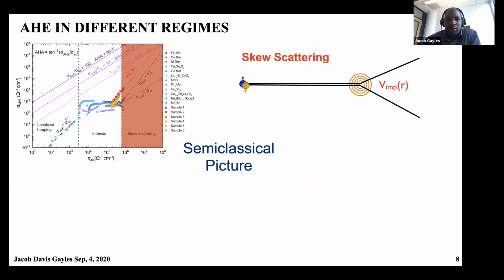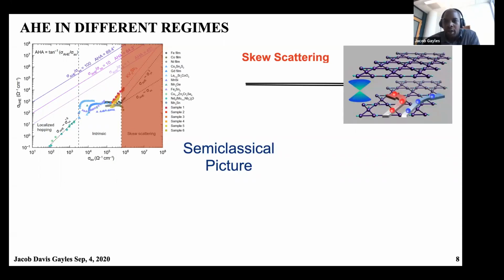Skew scattering is a picture of diffuse scattering that looks just like Mott scattering, where the spin of the electron is deflected by an impurity, and this impurity has a magnetic potential, so it deflects electrons with different spins in different directions. And this is usually defined in this high conductivity regime, where you have a small amount of carriers. But the border of this regime can actually be pushed to the left or right, and you see that you have this square scaling of the anomalous Hall conductivity. And recently, in a paper, we found that when you have a Kagome lattice with frustrated magnetism, the Dirac nature of the bands can actually supercharge these electrons to give you a very large anomalous Hall effect.